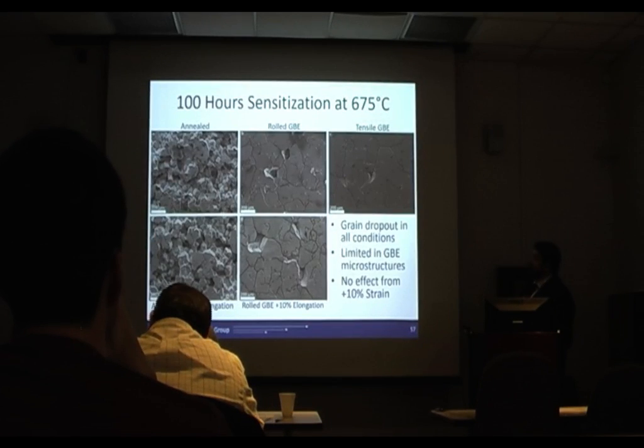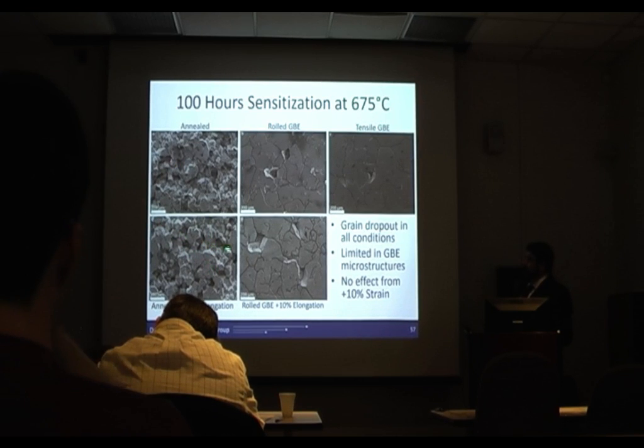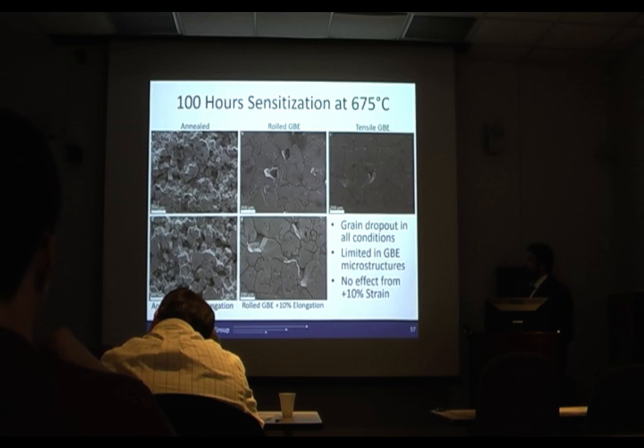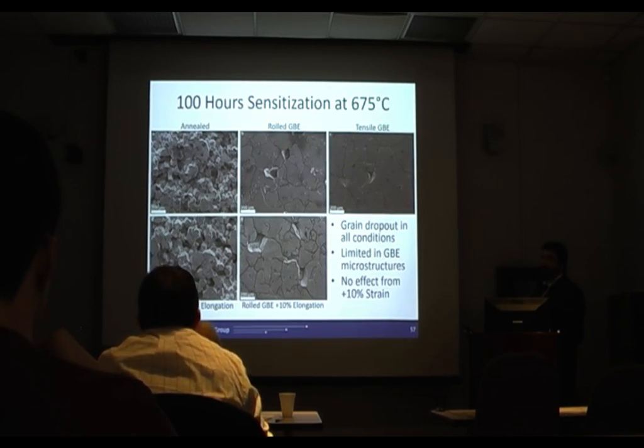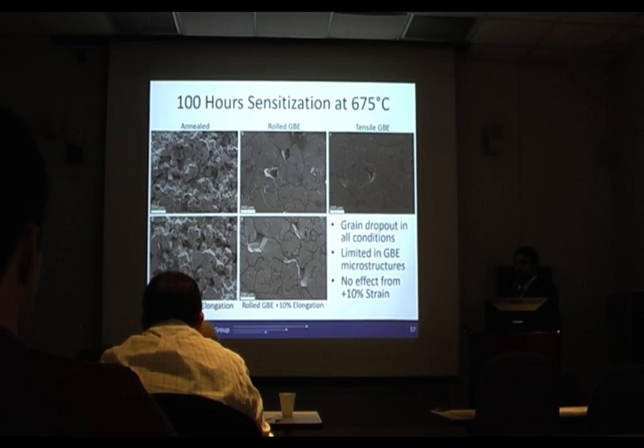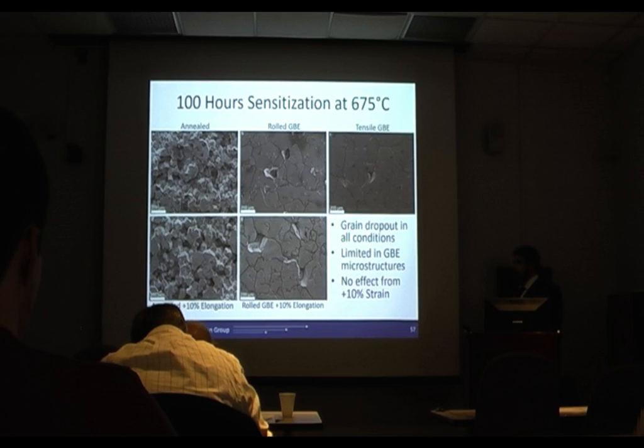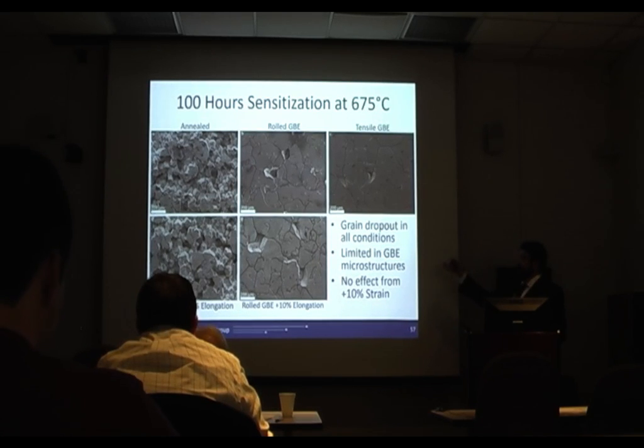When we move to the 100 hour, we can see that both the annealed and the annealed plus strain have extensive grain dropout, and in the other three microstructures, we do have some grain dropout, but it's nowhere near as extensive. This has been reported before in literature. This is one of the reasons that people have been examining the GBE microstructures, because especially under the standard test, they appear much more resistant.